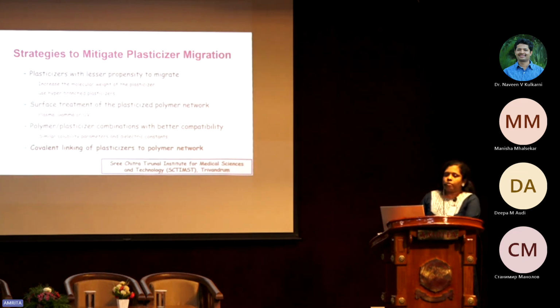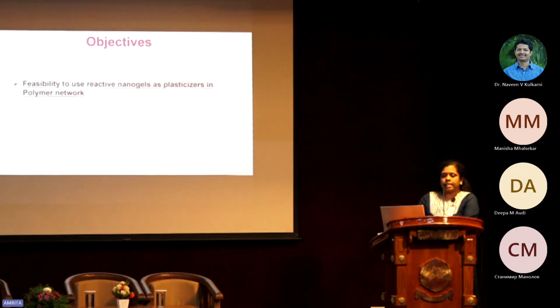And that is what we are also concentrating on, by introducing reactive nanogel additives. So the objective of the study is the feasibility of using the reactive nanogel as a plasticizer in the polymer network, so that it will be chemically conjugated to the polymer matrix. So there will not be any migration or leaching of the plasticizers, and that introduces no macroscopic changes in the particular matrix.